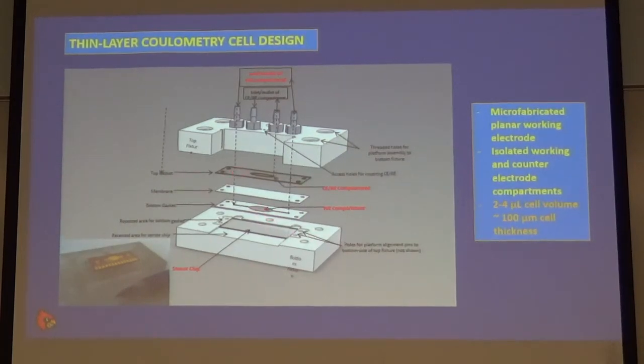Also, the height of that cell is usually about 100 to a few hundred microns. So it's a thin layer cell. Why do we want it to be thin layer? Well, after we fill it up and we apply a potential, electrochemistry only happens at the electrode surface, at the electrode solution interface. So a molecule that's way out here in solution doesn't get oxidized or reduced. It has to diffuse to the electrode surface. The thicker that cell is, the longer the diffusion time is, so the longer it'll take us to oxidize that entire sample cell. With 100 micron thickness for most species and most common diffusion coefficients, that means you can deplete that cell in less than a minute.